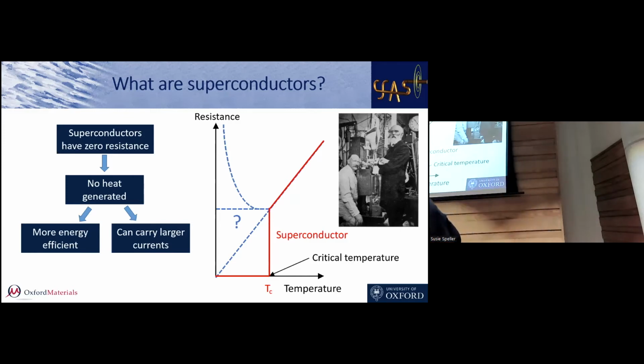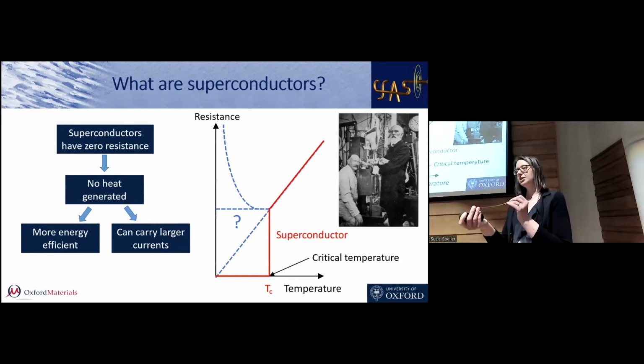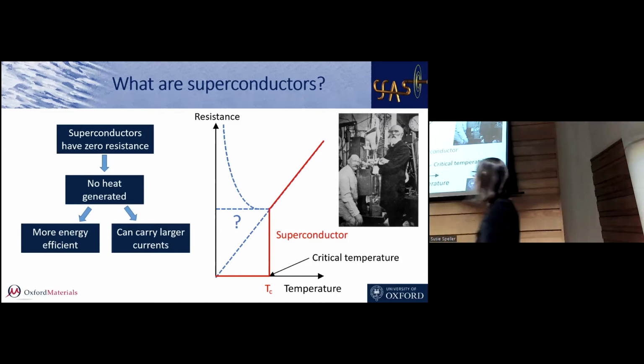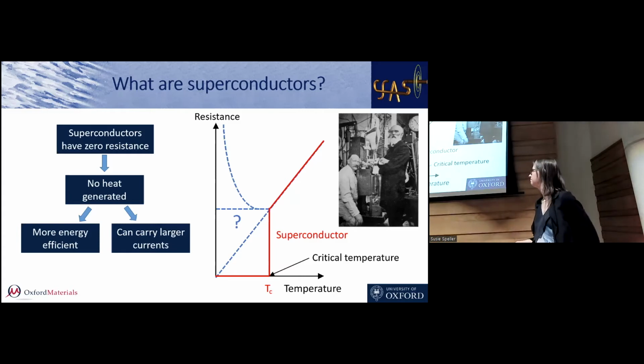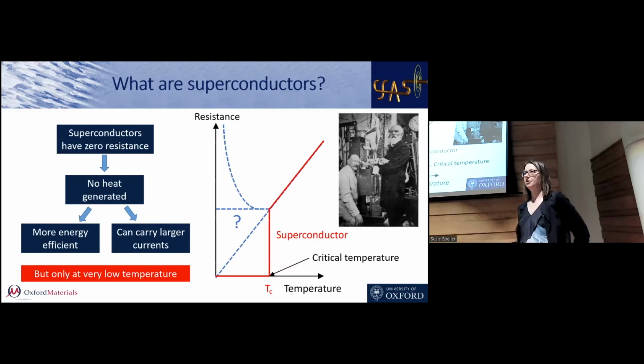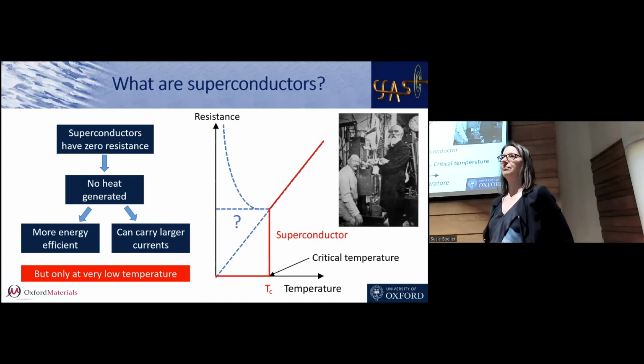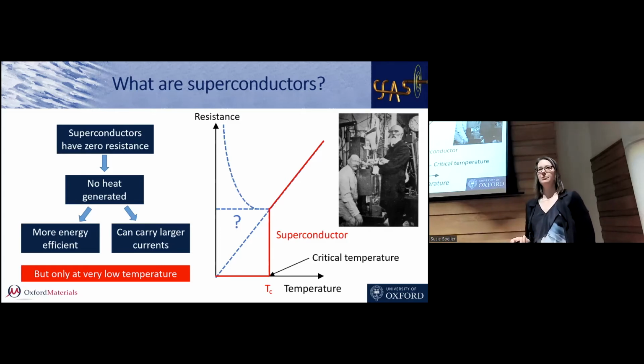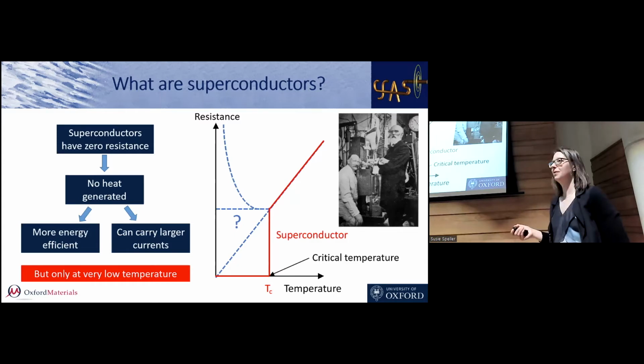So this piece of wire, if it was copper, it's got a cross-section of about 1 millimeter squared. If it's just copper, it will carry about 20 amps, maybe 10 to 20 amps. But this is actually a piece of niobium titanium superconductor. So at 4 Kelvin, it will carry probably near 1,000 amps. And that's what superconductors are really good for, carrying really high currents in really small spaces. Of course, there's the caveat that we've got to go down to low temperature to make them work. So if we could do this all at room temperature, then I think they'd be everywhere. And they would have been a long time ago. But we can only do them at very low temperature.